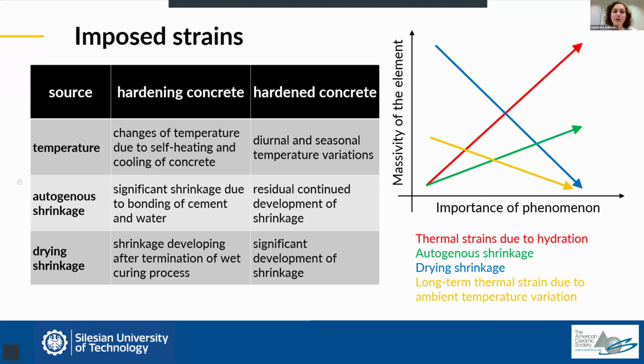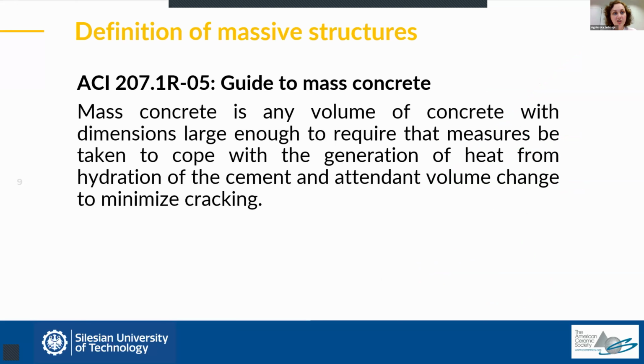And I said that usually we do not really understand what massivity is. But as engineers, we want to have some more quantifiable measures for massivity. And here comes a very nice and widely used definition of massive concrete that comes from the ACI guideline on mass concrete, which says that mass concrete is any volume of concrete whose dimensions are large enough that such a structure will require measures to be taken to cope with the generation of heat from hydration of cement and attendant volume changes to minimize cracking.